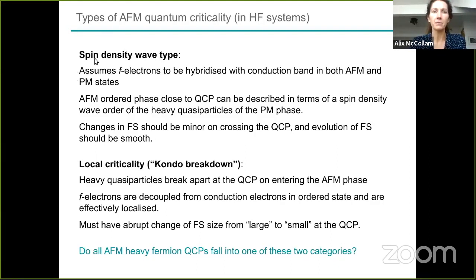One would be the spin density wave type. So this assumes that the f-electrons are hybridized with the conduction band in both the antiferromagnetic and the paramagnetic states. When you go through the phase transition, any change in the Fermi surface should be very minor and it should be smooth. So the ordered phase near the quantum phase transition can be just described in terms of a spin density wave of heavy quasiparticles. And then as that is suppressed, you go into a paramagnetic phase without too much change of the Fermi surface.